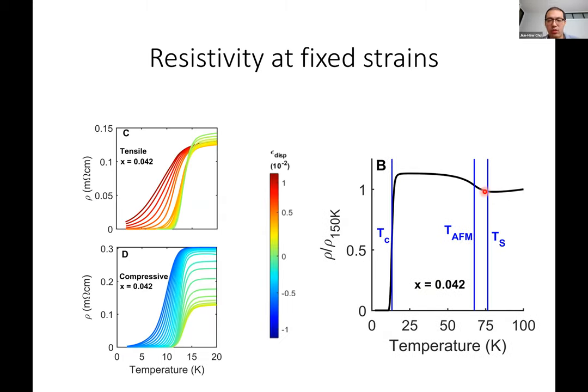We started to apply strain to this material, plotting the resistivity versus temperature below 20 Kelvin on the left-hand side. The strain state is color-coded: red corresponds to very tensile strain, and blue corresponds to very compressive strain. What you can see is that, first of all, in the yellow and green region, which is the smaller strain range, you don't see a lot of change of Tc. The resistance versus temperature curves drop at approximately the same temperature, 12 Kelvin.